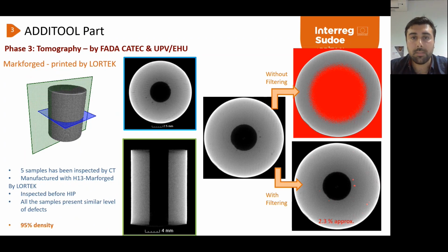Contrary to the Markforged, 5 samples have been inspected by tomography before HIP, and we have 95% of density. So we still have some porosities inside, but the density is quite good, and we are about the same densities as the binder jetting technologies.